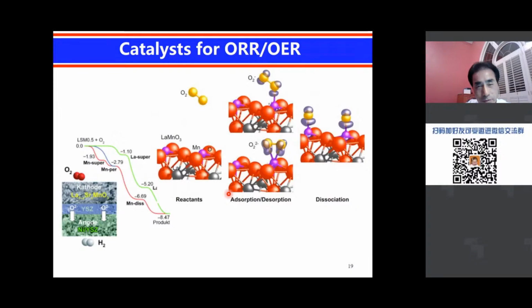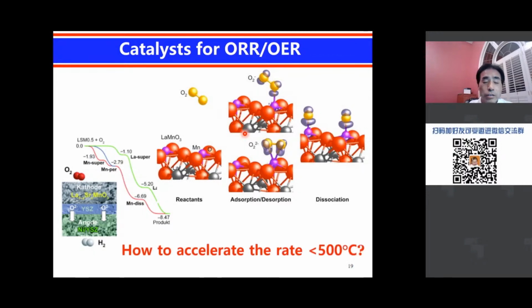Now, first, let's look at the air electrode. For the air electrode, when we operate a fuel cell to convert chemical fuel into electricity, here what we have is that the molecular oxygen comes into the cathode and first gets absorbed, dissociates, and then is reduced, eventually disappearing in the lattice. But this process is very sluggish, especially at lower temperatures. And so there are a lot of fundamental studies that have been done, trying to follow the elementary steps to understand the mechanism and rationally design a better surface. The key challenge is, how can we accelerate these processes at a temperature below 500 degrees C, or for the intermediate temperature fuel cells.